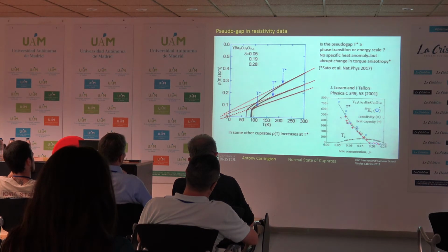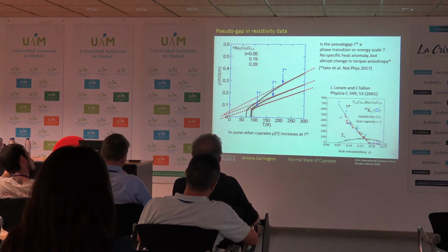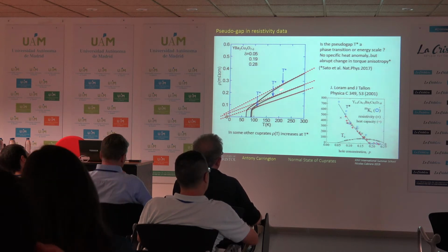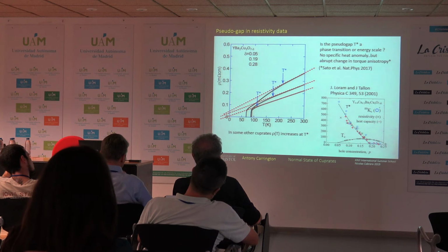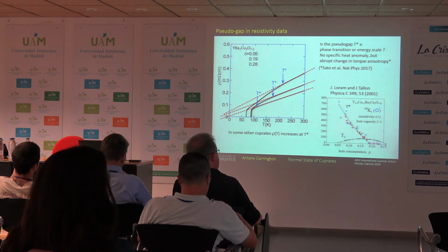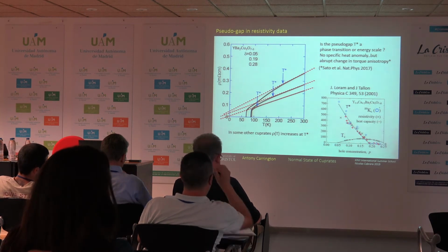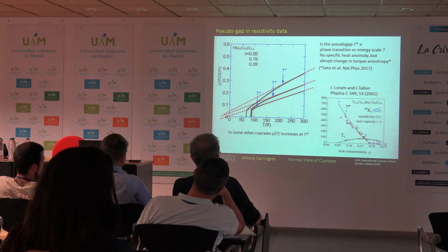Okay, so back to the underdoped behaviour for a minute. I said that this has this kind of an S shape. The interpretation of what's going on is that this decrease in the resistivity marks the onset of the so-called pseudo-gap. So what is the pseudo-gap? Well, it's been characterised by a number of different probes, but basically you can think of it as a depression of the density of states near the Fermi level.